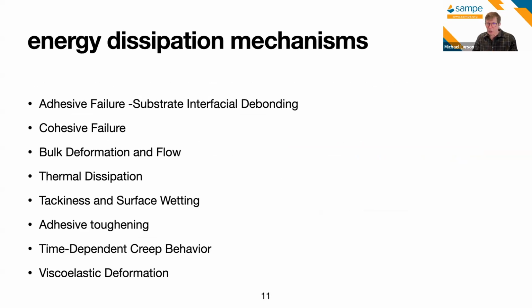This traditionally looks at the relative surface energies of the two surfaces involved. Cohesive failure, when our adhesive is failing itself, coming away, there's bulk deformation of flow, large strain kind of deformations. There are varying thermal dissipations associated with that work of failure, tackiness, surface wetting, adhesive toughening.